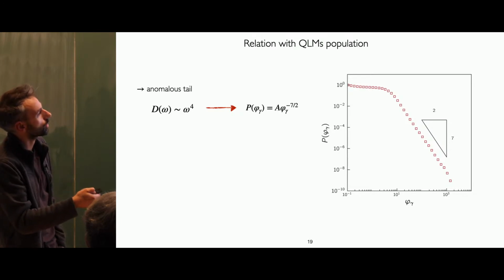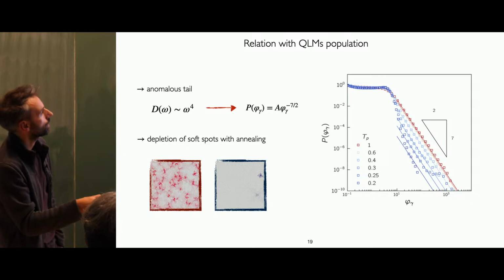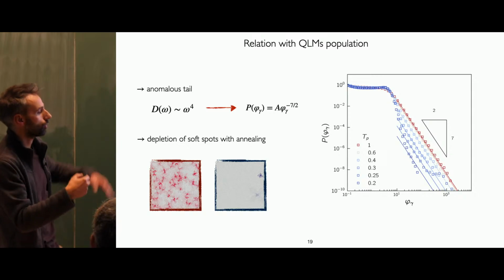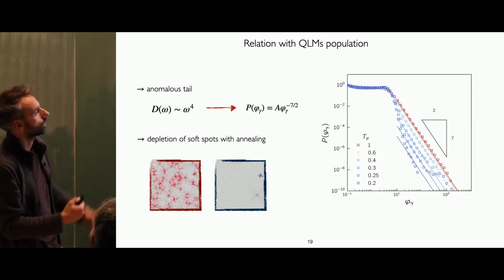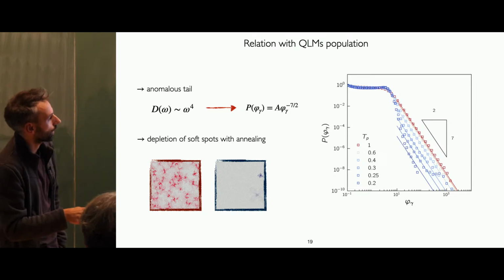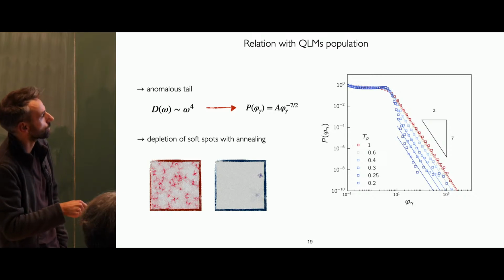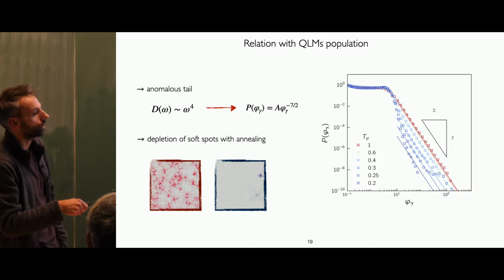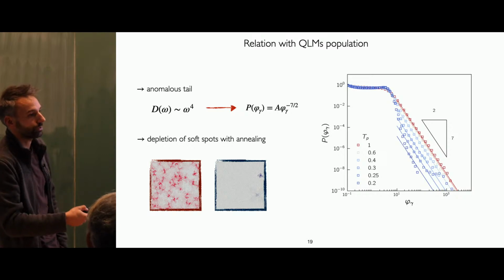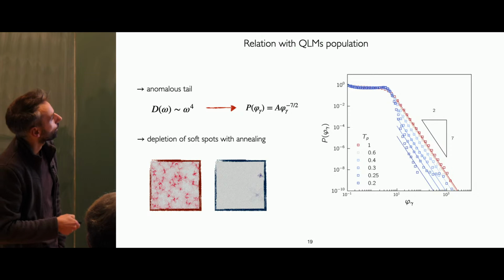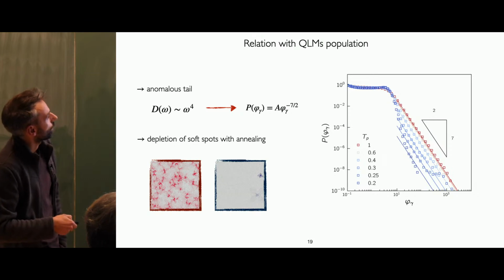and then you can ask, how does this tail change if I change something in my system? So here I'm changing the parent temperature, so it's the temperature at which I equilibrate my liquid using a swap Monte Carlo, and you see a depletion of this tail. And graphically, it's really like the same picture that I showed you at the beginning, a depletion of the number of soft modes that you have in your system.